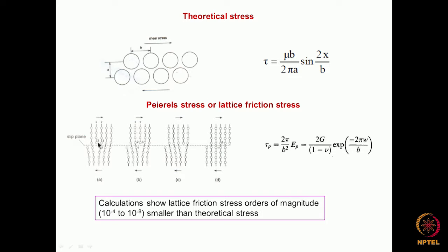So what have we done essentially? We have not moved any of these atom layers. By application of this stress, a small displacement has been created successively to either the top or both the top and the bottom layer in different directions, only at regions very close to the dislocation core. That way we are able to make the dislocation move. So the applied stress is doing work only in a very small region of this material, and as I had shown in the last slide, this is the value of the stress.